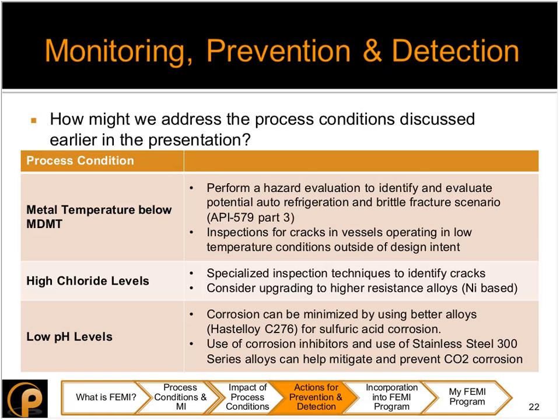When you have chloride stress corrosion cracking, you might have some specialized inspection techniques based upon the metallurgy. You might use dye penetrant or magnetic particle techniques to identify cracks that are on the surface. For volumetric cracks, you might have to use advanced ultrasonics or flaw detection methods like shear wave to find out what kind of cracks are present inside the volume of the material.